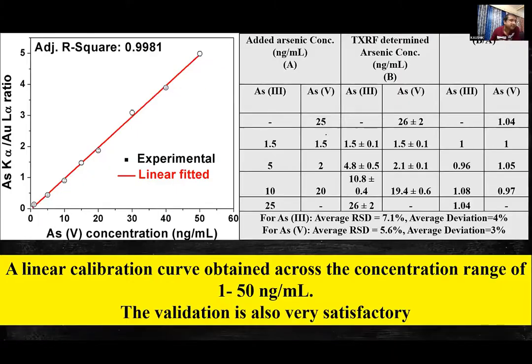After optimizing all these parameters, I finally prepared the calibration curve. The calibration curve is prepared by plotting the ratio of arsenic K alpha by gold L alpha, where gold is acting as an internal standard, and on the x-axis I have put the arsenic 5 concentration. I get a very linear curve, and by using the equation of that curve, I have determined the arsenic 5 concentration in different unknown solutions.